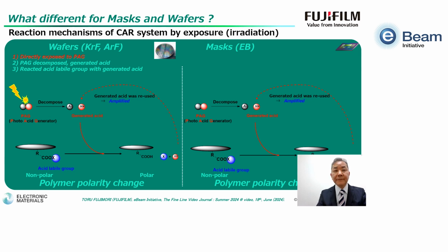On the other hand, in the case of masks, the electron beam is irradiated to the polymer matrix. Secondary electrons are generated from the matrix, and the PAG is decomposed by the secondary electrons. Then the reacted acid labile group will generate acid. This is the same. So the initial reaction is different.